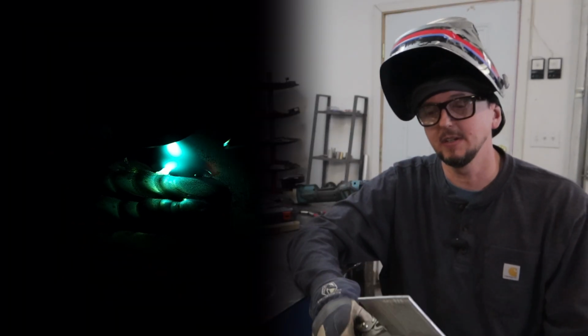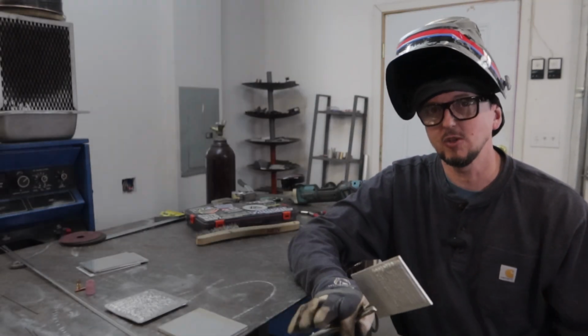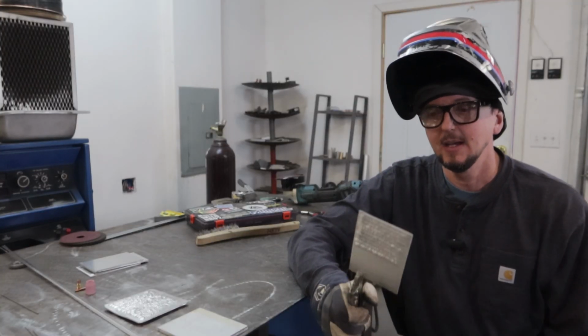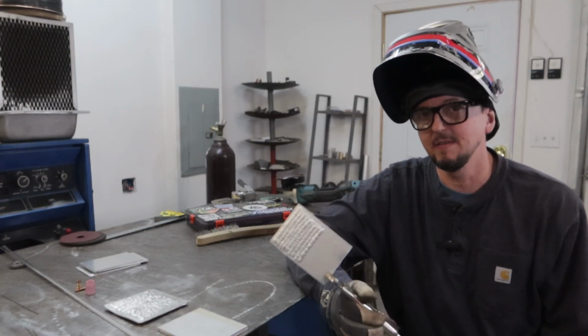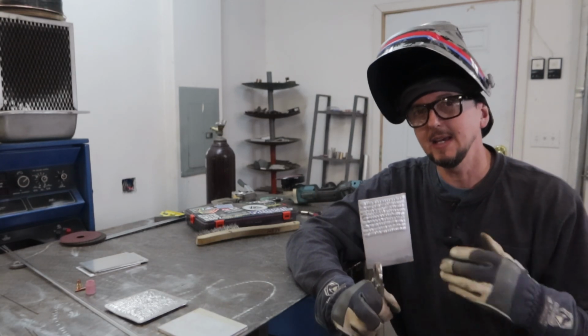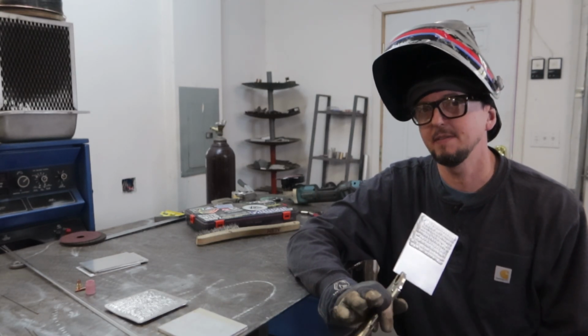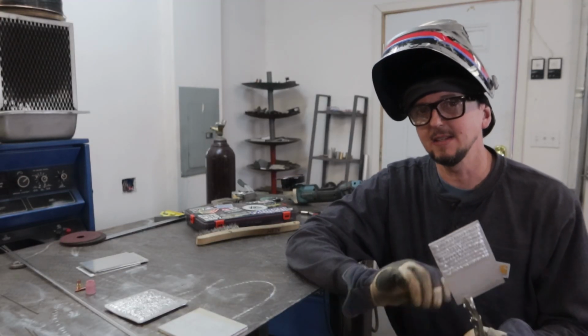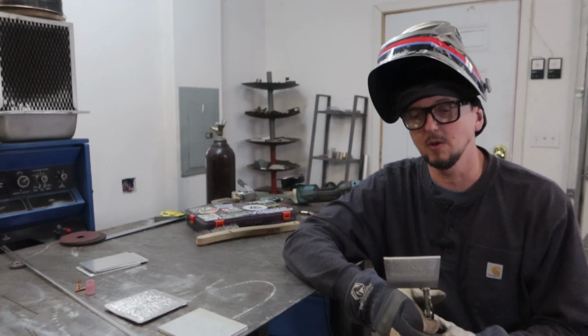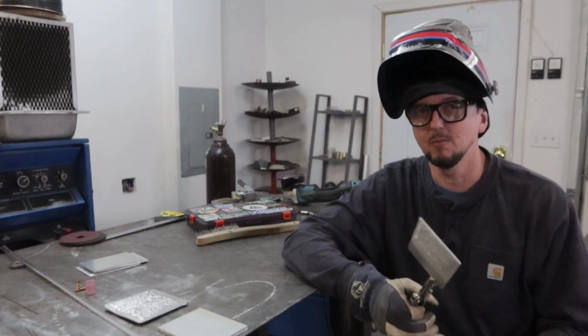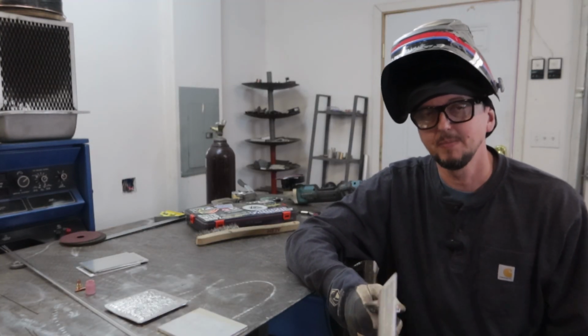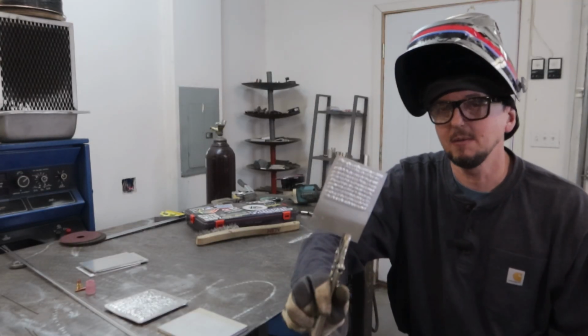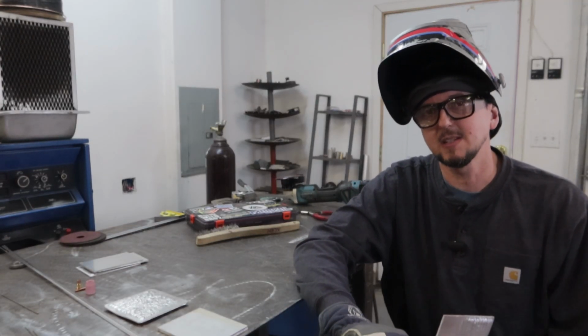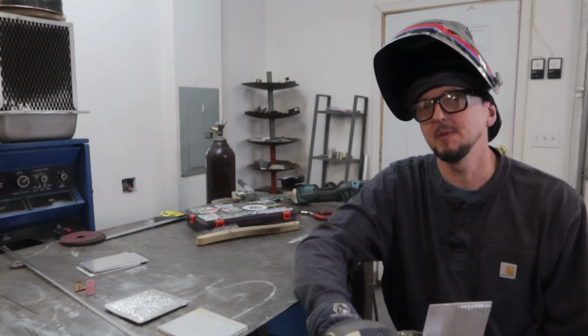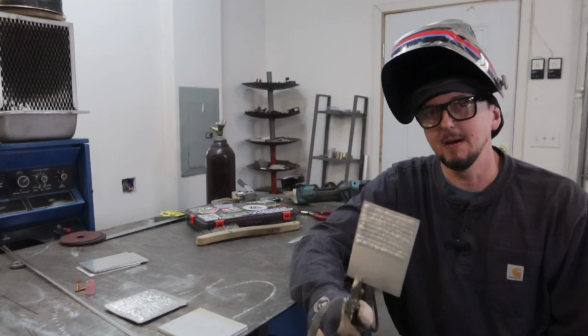Okay, you can quench these, but you're adding a lot of hydrogen to your material, and if you don't let it sit and you don't let it completely dry out, then you're going to get contamination. Moisture is not aluminum's friend, and it's very porous. So in the welding process, you're better off not quenching. At the end, if you just want to cool it off quickly, then you can quench it. But if you're still going to be doing some welding on it, you don't want to add that moisture to the material. Okay, so just keep working on it, but always with welding, slow is fast. Don't be in a hurry, let it cool down in between, and you'll have a lot better luck, okay?